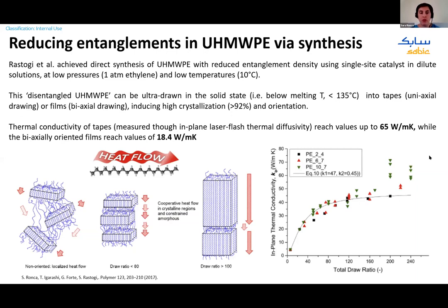So when we measured the thermal conductivity of these tapes with in-plane laser flash thermal diffusivity, we found that we could reach values up to 65 watt per meter Kelvin when the polymer used had, as you can see in the graph on the right, a molecular weight of 10 million grams per mole. So with lower molecular weight, we were reaching up to 45 to 50 watt per meter Kelvin.